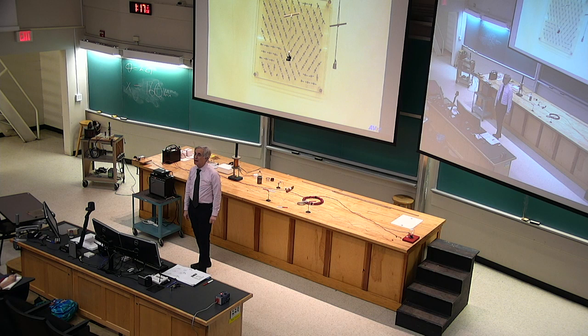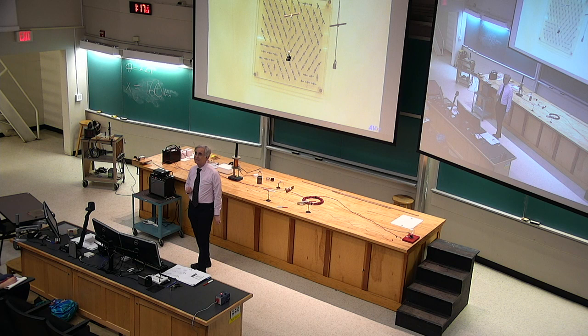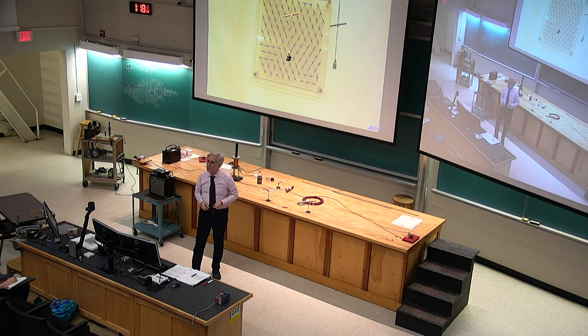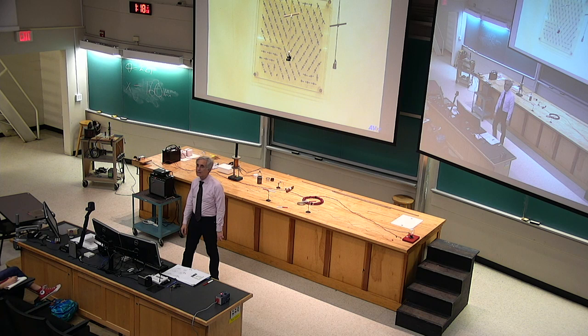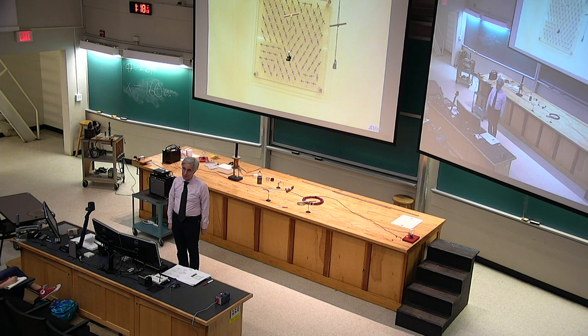Any material, hard or soft, you can ruin its magnetization by mucking with the domains. How? Hit it with a hammer — hammers are not good for magnets, not because you can break them, but because you pump in energy and shake things up. Pounding a magnet will weaken its magnetization. Thermal energy — put many magnets in the oven and you kill them; they have a temperature above which they give up and forget. You can also upset them by exposing them to external magnetic influences.